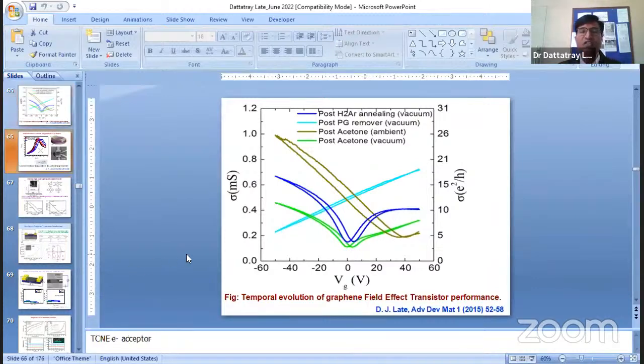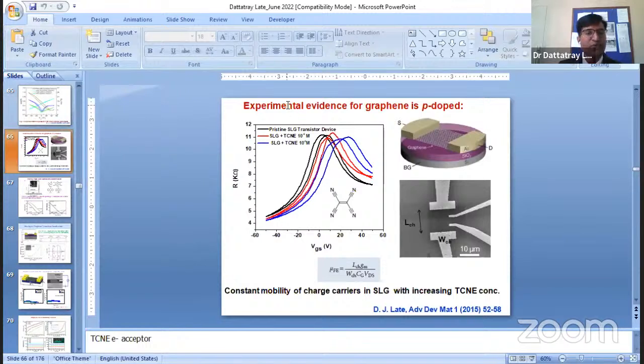Now what we have done here, to prove our theme: can you make graphene more P-type, or can you make graphene more N-type? So again, we have recorded the electrical measurement. The pristine single layer graphene shows ambipolar behavior, right? And the Dirac point is exactly at 0. Now we have started adding TCNE at concentrations of, for example, 10 raised to minus 6 molar, minus 8 molar, and so on.